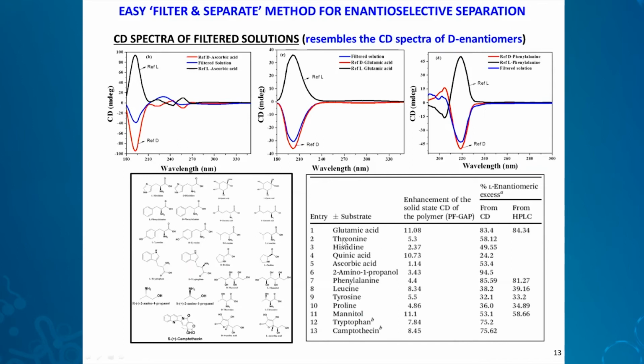So we have used several classes of materials, ranging from sugars to alcohols to amino acids, to test the enantiomeric separation in this way. That is, you take the polymer powder and put it into an equimolar enantiomeric mixture of D and L isomers of these various families of materials. And then after 48 hours, filter and remove the polymer. Then evaluate the CD spectrum of the remaining solution. And we find that the solution is rich in the D isomer because the L isomer is taken up by the polymer. So for various molecules used, you find various percentage enantiomeric excess, as shown in the table here.